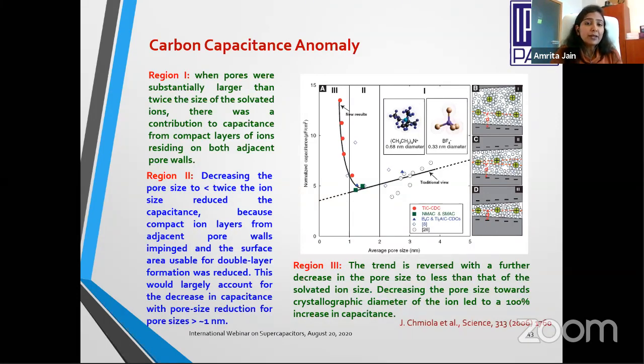When we go to region 2, you can see that all of a sudden there is an abnormality, a capacitance value which shot up. It was an interesting study carried out by J. Chmiola et al. in 2006, where they showed that at certain nanometer levels, for example in this case at 1 nanometer, we got an exceptionally high capacitance value. It might be because of a perfect switching in and switching out of ions. So we need to be careful that the compatibility of electrode material and electrolyte material, in terms of their ionic sizes, matters a lot.